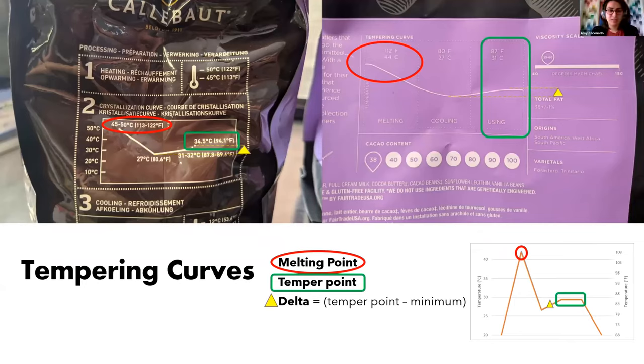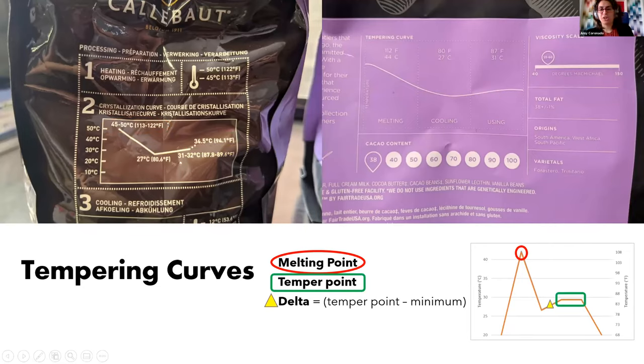Yeah, those are both great questions. So the 34.5, let me go to a picture where it doesn't have all this stuff written on it. The 34.5 here is the upper working temperature that you can use. They're basically saying don't go above that temperature when you're working the chocolate, or it will melt away all of the precious seed crystals that you worked so hard to make, and then you'll get that under-crystallized chocolate that blooms that I was showing earlier. This range of temperatures is a good working temperature, but if your chocolate starts to over-crystallize, if it starts to solidify too fast, then you can go up to this temperature before you melt away those beta 5 crystals. But if you go above that, then you're going to start to be in trouble.